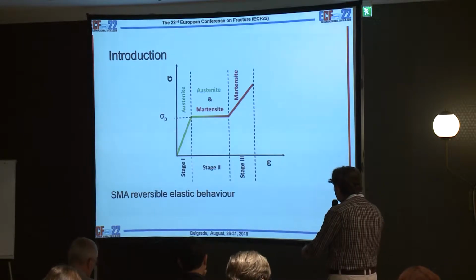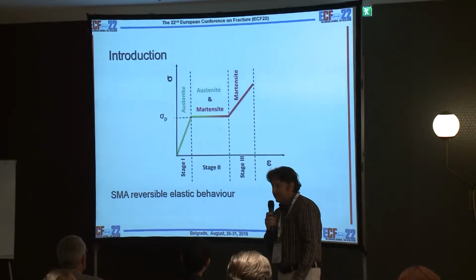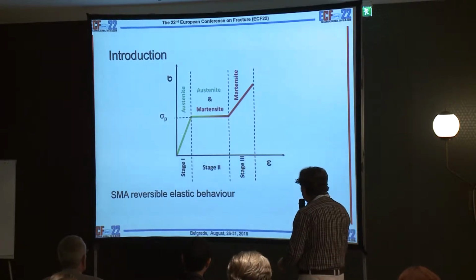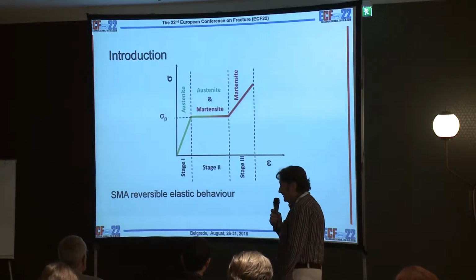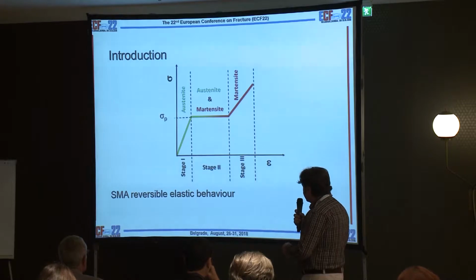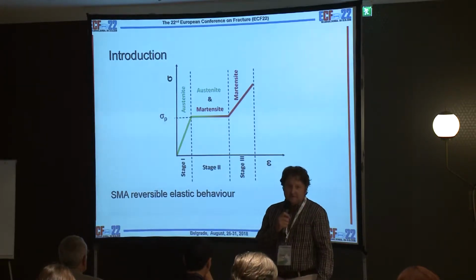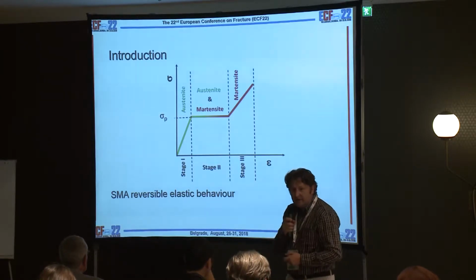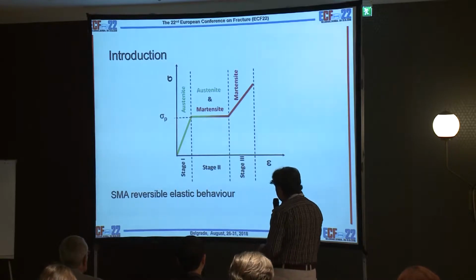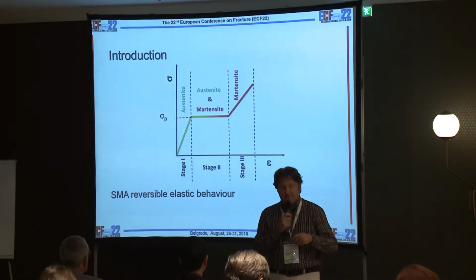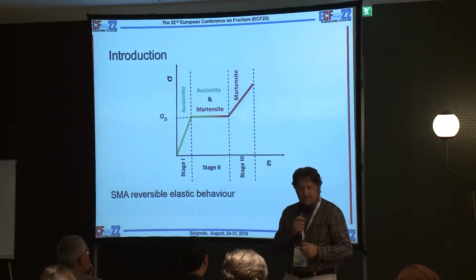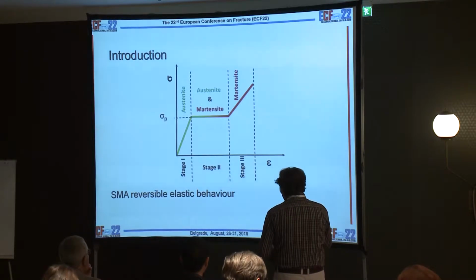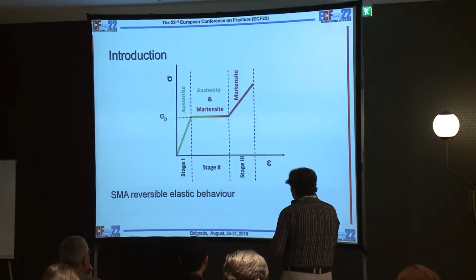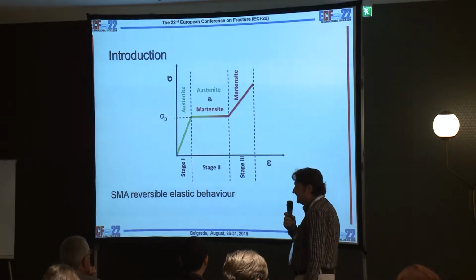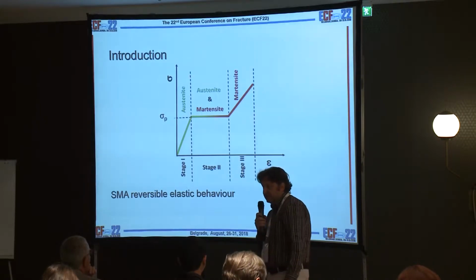In the first stage, we can see a typical elastic stage characterized by the austenite Young modulus. This structure is able to sustain stresses up to sigma p values. This is the level of stress where the transformation from austenite to martensite takes place. The second stage is characterized by this transformation. Sometimes it is schematized as a plateau, but in real results we have just a little bit of slope. When all the austenite has transformed to martensite, we have another elastic stage, characterized by another Young modulus, because it is another material.